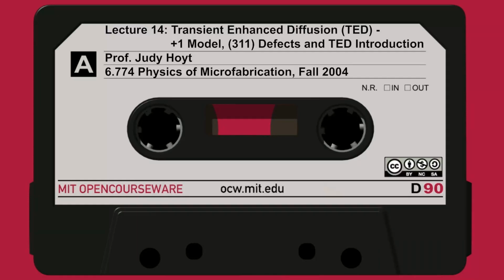And then after 1 minute at 750, this is how the boron has diffused, the black line. And look at 1 minute at 750, the dashed line refers to the right-hand axis. Sorry, you should write that in. So this dashed line is to the right-hand axis. That's the interstitial supersaturation ratio. At 750, it's about 10 to the 4th. And it's pretty uniform throughout the sample.